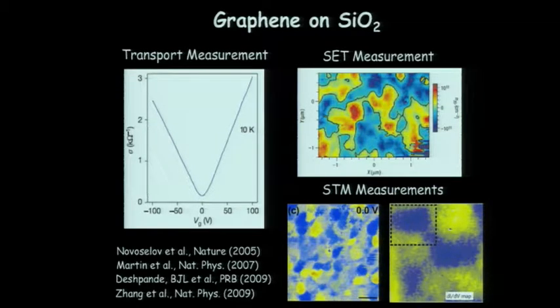And you can also go and look at this. This is on the sort of micron scale. If you go down and look on the nanometer scale, you see the same thing. There's a strong disorder in the silicon oxide substrate, and it's coming from the impurities that are trapped in the oxide. And so to get rid of this, we wanted to use a different substrate.